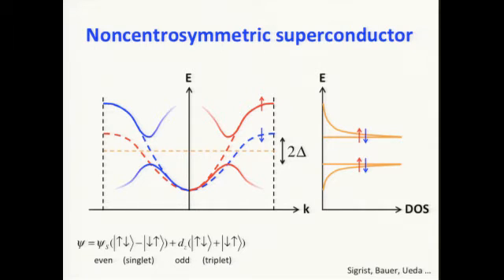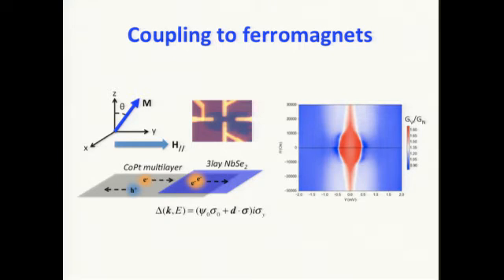Okay. Sorry, I have a last question. Do you think this mixed pairing will give you some unique Andreev reflection? Oh yes, I sort of skipped that. This is this one here. When you couple to a ferromagnet, the differential conductance due to Andreev reflection would depend on the magnetization direction, because you have this triplet component which is characterized by a d vector here, and the d vector is out of plane in this material, so it depends on the relative orientation of the magnetization with respect to the d vector.